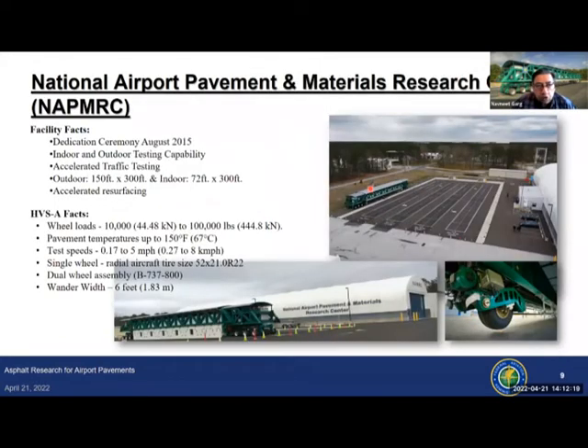So to look at the effect of these increased tire pressures and wheel loads on asphalt pavements, since we could not test at higher temperatures at NAPTF, NAPMRC was developed and built in 2015. Because for surface layers, you're not really interested in the whole landing gear, because you see minimum wheel load interaction taking place for the surface layers.